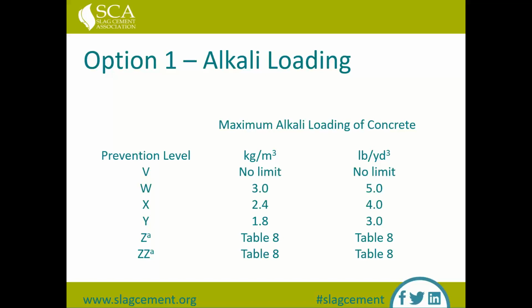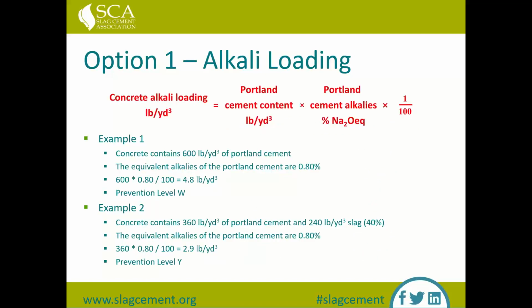How do we calculate the alkali loading? It's a simple calculation: multiply the Portland cement content of your mix times the Portland cement alkali content, divided by 100. For example, if we've got a concrete that contains 600 pounds per cubic yard of Portland cement and the equivalent alkalis—the combination of sodium and potassium in your Portland cement—are at 0.8%, multiply 600 times 0.8 divided by 100, giving you 4.8 pounds per cubic yard. Comparing that to the previous slide, that puts you at prevention level W, since we have not exceeded 5 pounds per cubic yard.